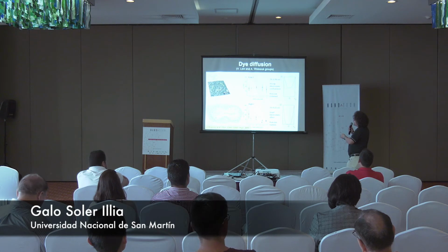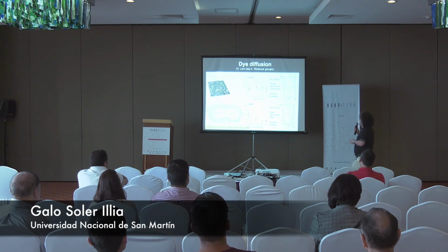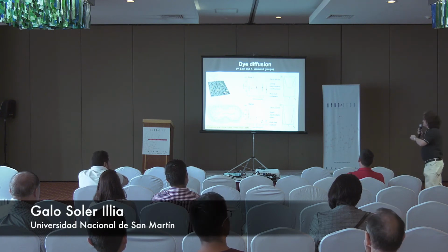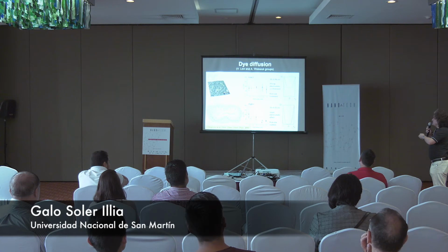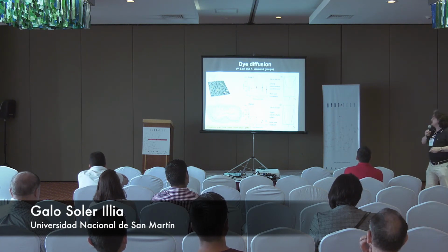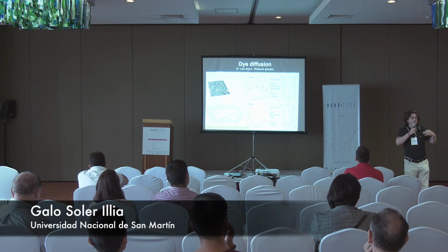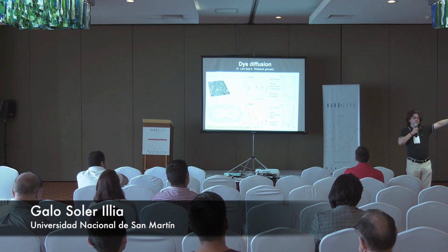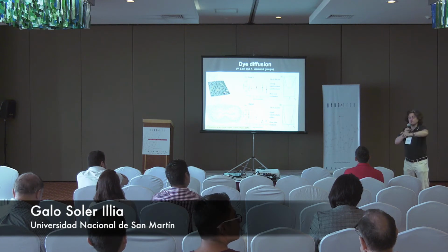A long residence time means that the molecule is moving very slowly. Here we vary systematically the pore and the neck diameter, and we find that the molecule is quite trapped. It's not moving a lot, the movement is quite slow, and it's not depending on the pore size. Why? Because the ionic force is low, so the electrostatics of the system keeps the molecule hanging on the wall. So the movement is very slow.